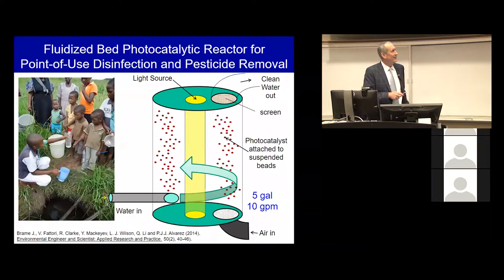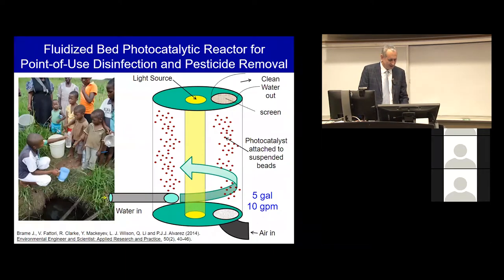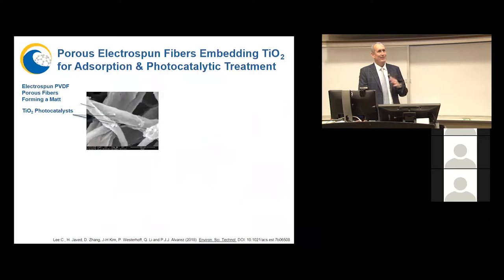And this is a 5-gallon reactor, meaning that you can take it with you on a plane. And with a contact time of 30 seconds, you were able to produce 10 gallons per minute, which is enough to provide water for 15 households. So it worked really well. It's encouraging. Of course, this bait and hook approach that we talked about earlier, there are more sophisticated ways to